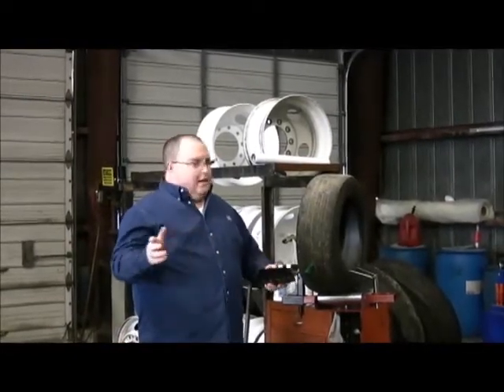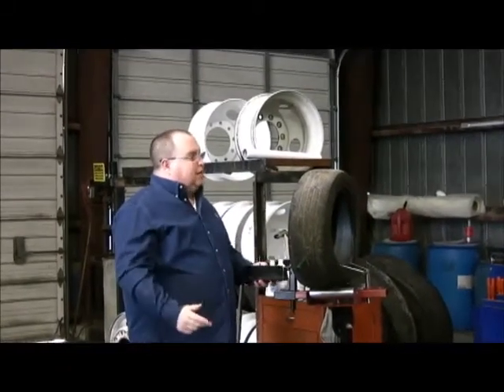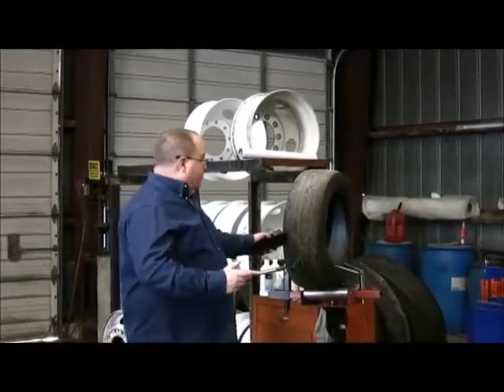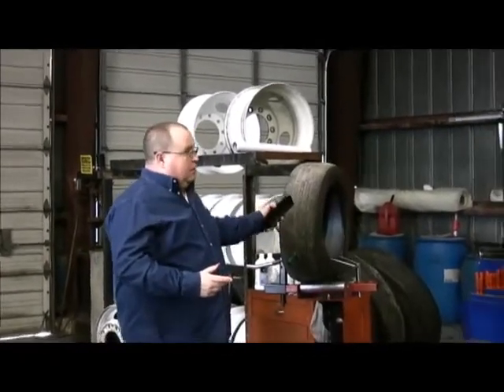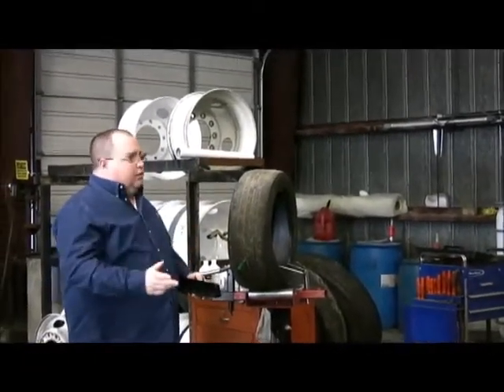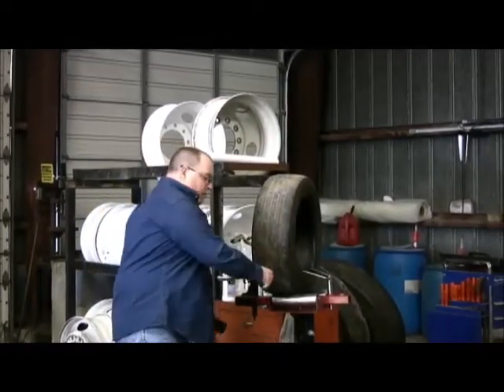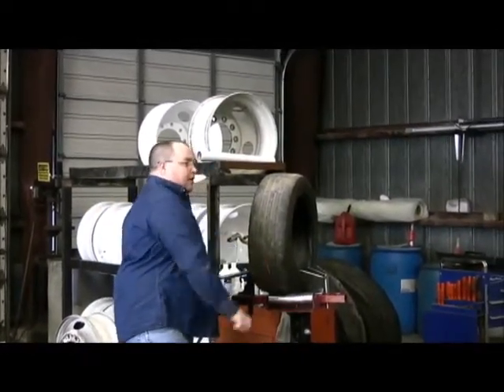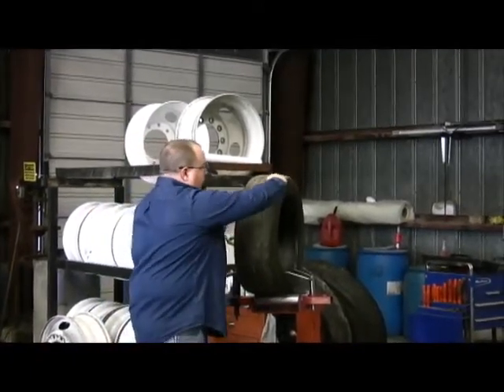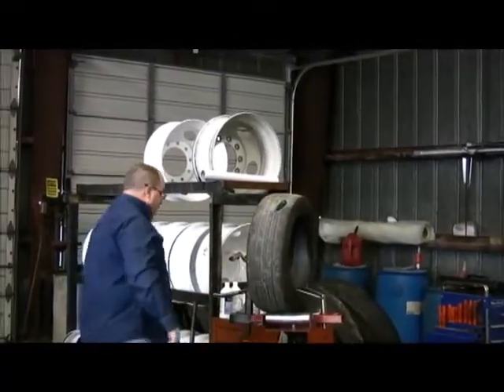All right. That can work in a passenger, light truck, truck tires, depending on the size of the hole, okay? Like I said, just intermediate year. The heavy trucks, you go up one more size to 3/8. One piece repair, angle of injury is 15 degrees or less, okay? A lot of truck shops opt to only use a 2-piece. Greater than 15 degrees angle of injury. Okay?